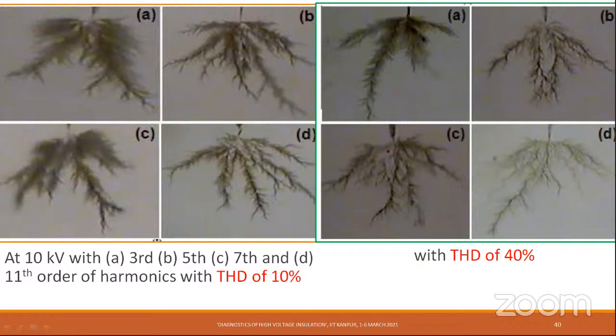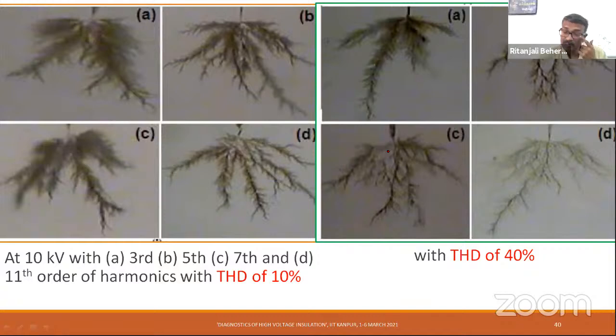Okay. And one more question, sir. You have said that after 3 volume fraction, percolation happens. Till 5 volume fraction, when we use nanocomposite, it is too early to get percolation. Sir, can you please explain that? No, but the same thing we have observed even in the case of thin films. Up to 3 weight percentage, there is a good breakdown strength. But when we cross 3, then breakdown occurs very quickly. This is for almost all three, magnesium oxide, alumina, we have observed.